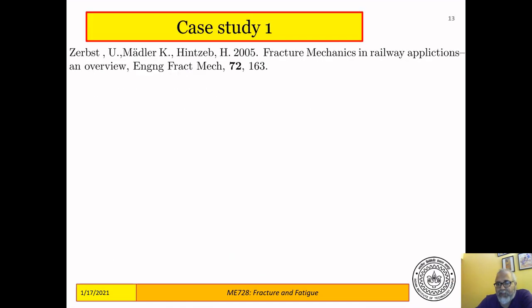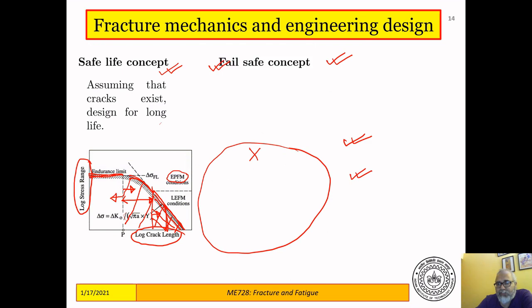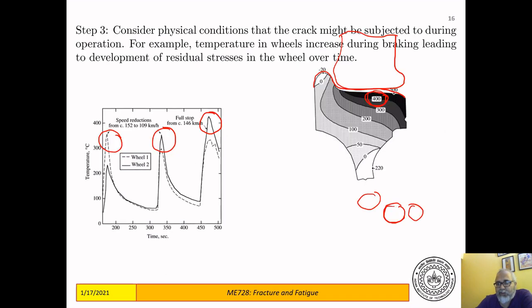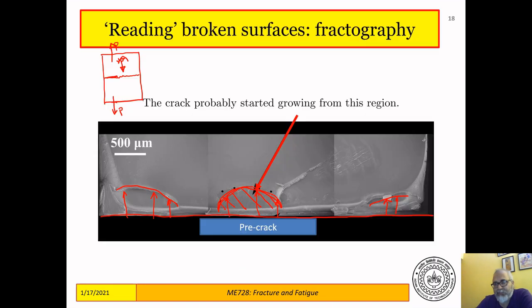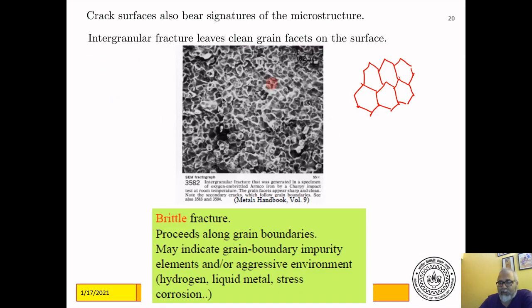So if you have intergranular fractures, then one of the surfaces would bear the signature of the grain boundaries. Well, both surfaces would bear signatures of the grain boundaries, because the crack is growing, say, like this, and taking whole grains out. So these are those signatures. So when the crack surface is full of depressions or cavities which are of the size of the grains, then with clean grain facets on the surface, you know that it's intergranular fracture that has happened.